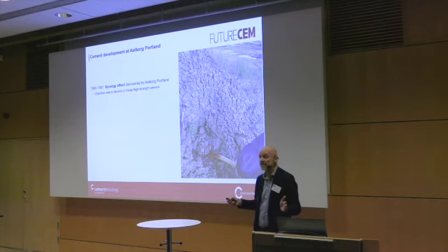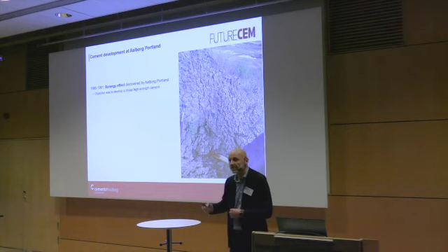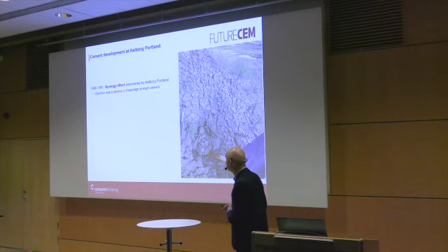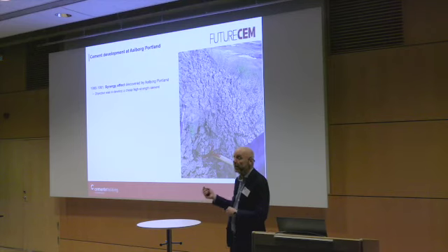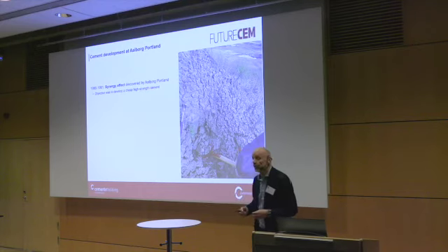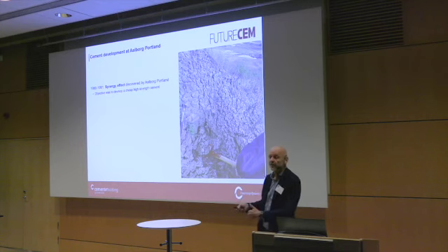And we did a lot of tests, tried the limestone, tried all sorts of other things like crushed bottles, volcanic ash, whatever we could get. And then we came across the synergy effect that showed us this was interesting. But what happened was that the limestone cement was good enough. We put that on the market, and therefore we put the other stuff in the cupboard and waited for better times.